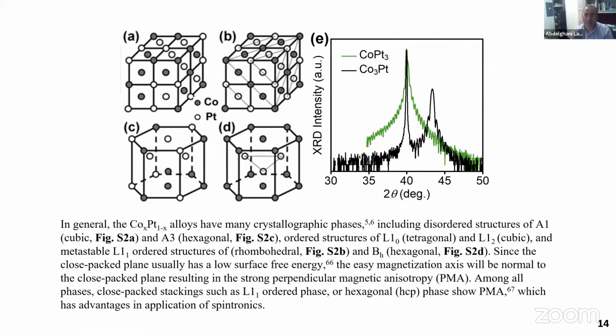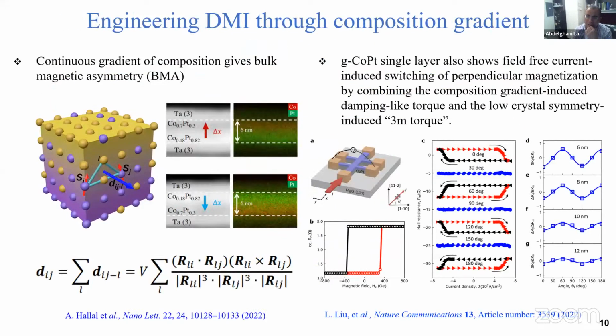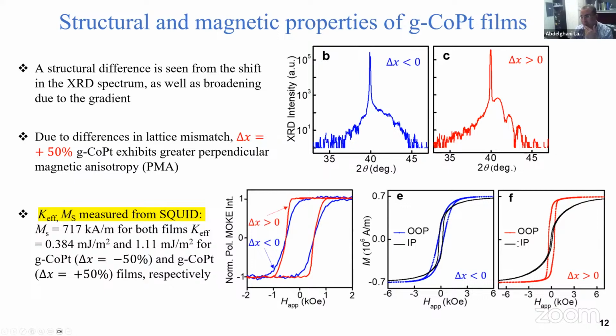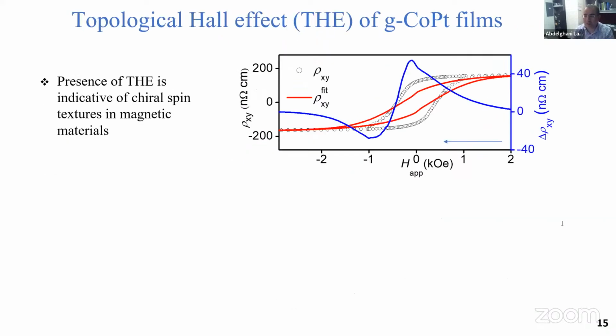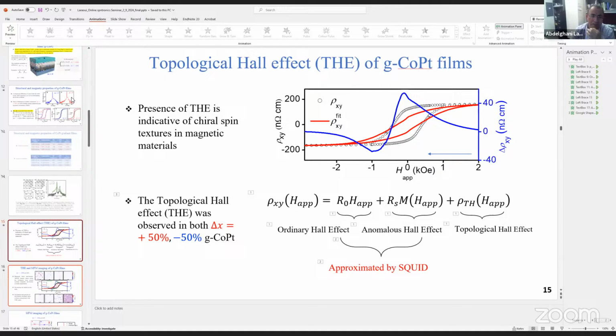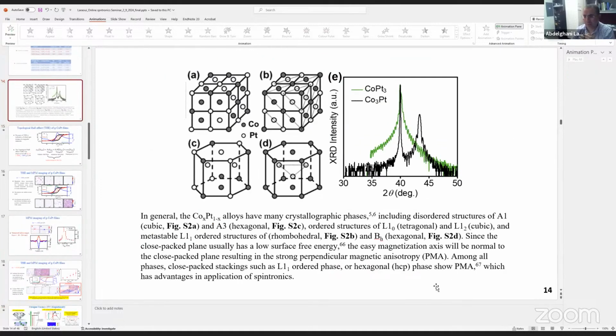To be honest, we did this in principle because we tried to explain why the magnetic anisotropy changes. For certain positive gradients, for example, you see the magnetic anisotropy is weaker. Then our colleagues did some detailed XRD, and I just showed one of the slides. I cannot answer the question directly, but we think there are mixtures of different crystal structures, which change depending on whether you go from cobalt platinum 3 or cobalt 3 platinum.